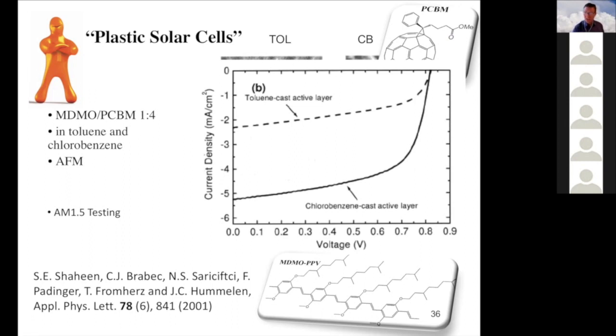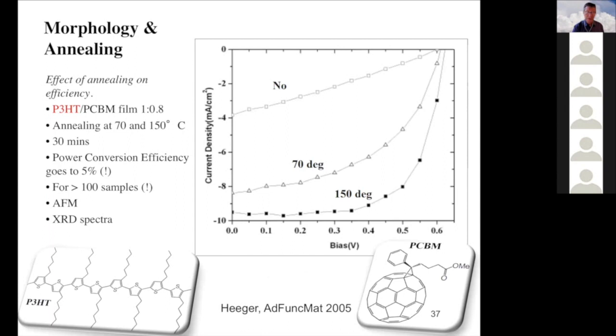You can change the nanoscale morphology of an organic solar cell by changing the solvent or even using a co-solvent, an extra solvent. You can also heat a film for a limited time in vacuum, and it can also result in an efficiency increase. Here you see these typical current-voltage plots. This is not a good cell. If you heat your device for half an hour at 150 degrees, then the efficiency increases a lot. And you can see that from this current-voltage plot.